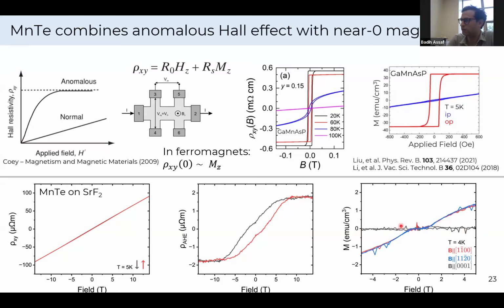Notice one more thing here. The values of magnetization are something like an order of magnitude to a factor of 50 smaller than what we see on gallium manganese arsenide. The spontaneous value of magnetization is almost absent in manganese telluride. It's at least 2 or 3 orders of magnitude lower than gallium manganese arsenide phosphide.